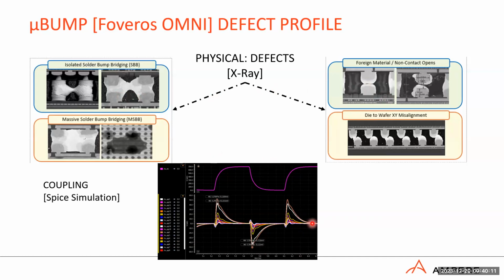And this one is an example of something that we showed. This is actually from a design. It's very design specific, for a 25 micron, 3D or 2.5D design with an interposer, where the spice netlist of the interconnect was actually extracted and a simulation was done. So this is for 20 adjacent wires. What they did here was toggle one of the wires at the rated speed, and everything else was held constant.